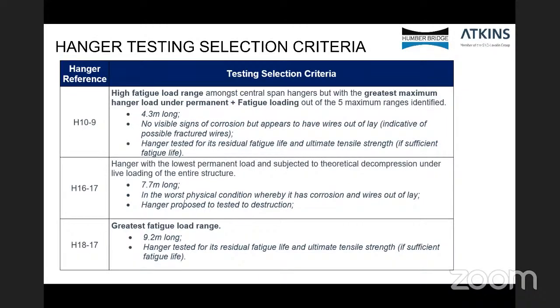So these were the choice of hangers. Hanger 10-9 had the highest fatigue load range amongst the central span hangers, and it was the greatest maximum load under permanent and fatigue loading. It was 4.3 meters long. There were no visible signs of corrosion, but it appears to have wires out of lay, indicative of possible wire fractures, which was a particular concern that we wanted to assess during the assessment. The hanger was tested for its residual fatigue life and ultimate tensile strength.